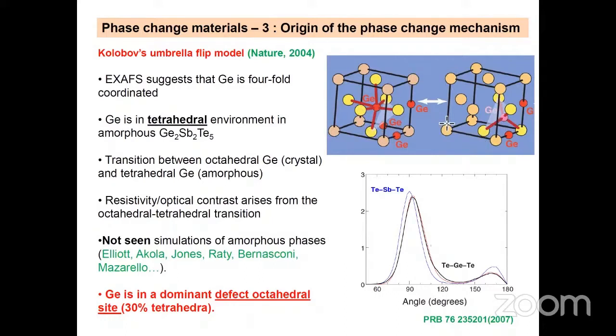Essentially, various groups performed quenched glasses using DFT calculations, and they could show, that's the figure that you can see here, that if you look at the bond angle distribution around germanium, it looks pretty much the same as the one that you can obtain for an antimony centered bond angle distribution. And they display basically two features, a main peak at 90 degrees and a secondary peak close to 160, 180 degrees, which clearly signals that the system is octahedral, that germanium is octahedral. And actually, the main conclusion was that this umbrella flip model is probably not valid, first point. And the second point is that germanium is in a dominantly defect octahedral site.